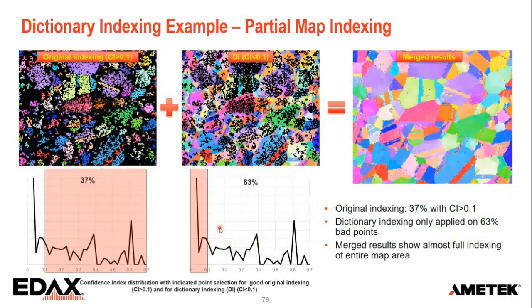So just to show that in a little bit more detail, here the original indexing, where we apply a CI filter of 0.1 again, is about 37% was correct. When we flip the filter, so only looking at the bad points, that's 63% of the total surface area, there we can do the dictionary indexing and then merge those results. And again, you get a good data set that you can use for most of the crystallographic and morphological analysis.